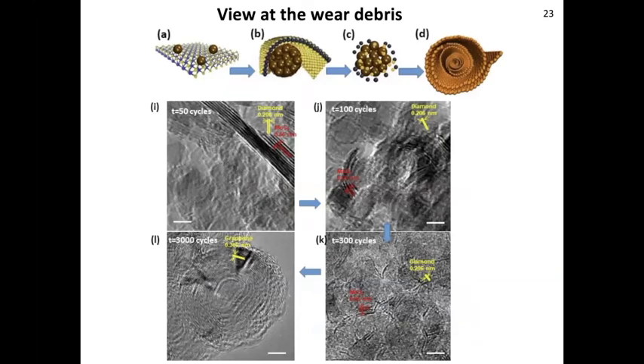We went again to the TEM analysis of our systems and this is what we observed. Pretty much in the beginning of sliding, after 50 cycles when we stopped the test, our system consisted of diamond nanoparticles and MoS2 flakes. You see this diamond lattice, somehow the contrast doesn't show as nicely, but we see these diamond lattices and we see the large spacing of the MoS2 flakes.